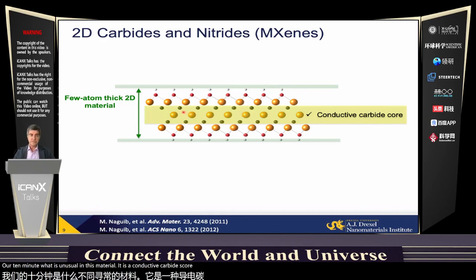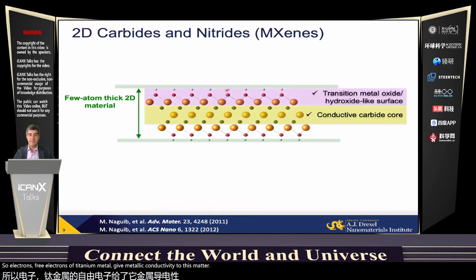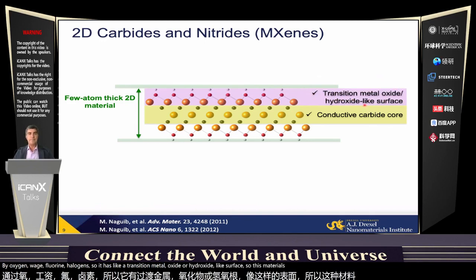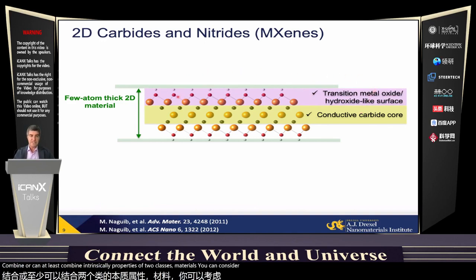So the free electrons of titanium metal give metallic conductivity to this material. But at the same time, the surface of MXene is usually terminated by oxygen, OH, fluorine, halogens. So it has a transition metal oxide or hydroxide-like surface. So these materials combine, or can at least combine, intrinsically the properties of two classes of materials. You can consider them to be like a conducting clay or ceramic oxide, or you can look at them as, for example, a water-soluble metal, because these functionalities provide hydrophilicity and solubility to this material.